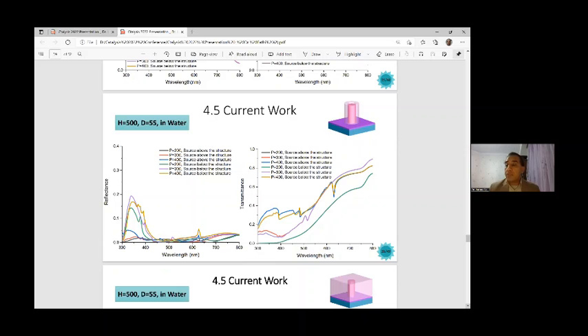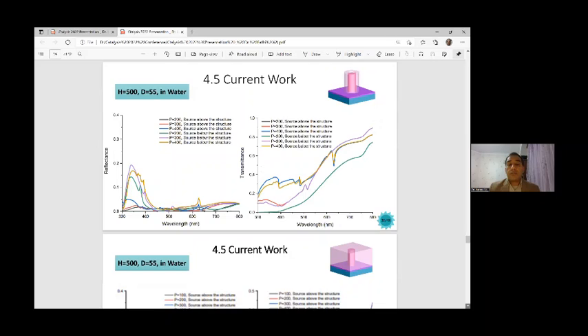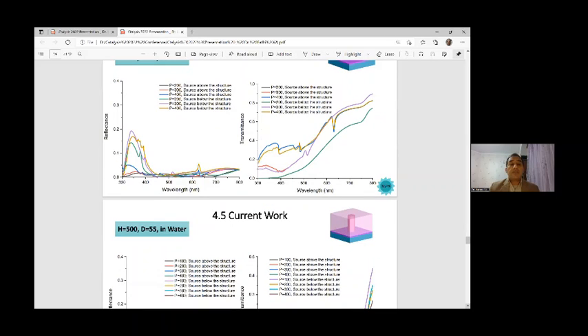To understand the reason for the reflectance and transmittance, in slides 36 and 37 you can see the curves of reflectance and transmittance for the two structures, 2 and 3. Also here, we examine only one of the nanorod dimensions, the diameter of 55 nanometers and the height of 500 nanometers, in a water environment. According to the figures, they all follow the same rule. It is not required to check all of the figures.